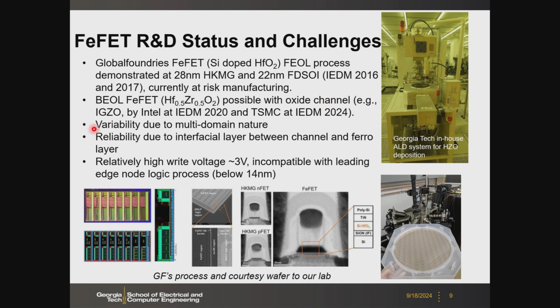There are some challenges moving forward for FE-FET technology. One of them is variability, especially when you scale down the technology node and the size of the gate area. That will matter because of the multi-domain nature of the ferroelectric, especially when the ferroelectric thickness is about 10 nanometers. Another challenge is reliability, especially for the front-end-of-line silicon channel. Then you have the interfacial layer between the ferroelectric and the channel.